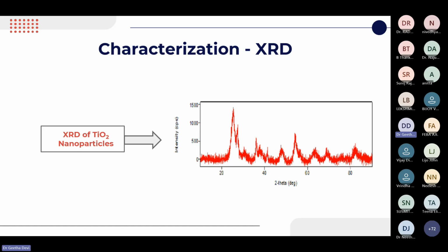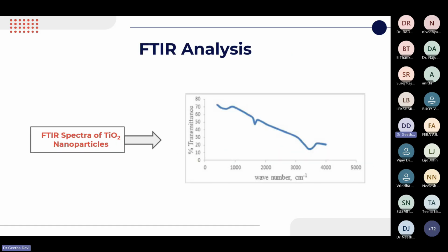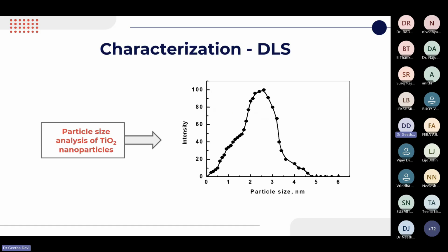These different peaks represent the XRD analysis, that is, it shows it is crystalline in nature. This is the FTIR spectroscopic image, and the particle size analysis shows that the average particle size is almost 0 to 5 nanometers, which indicates the good quality of the synthesis method.